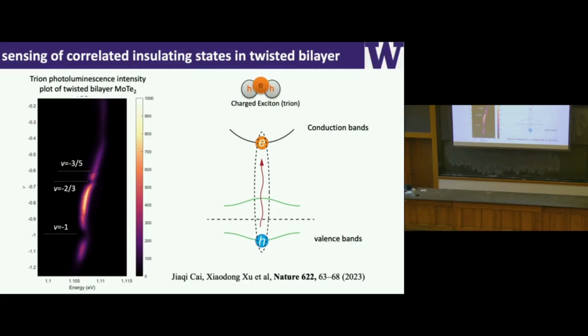Just to give you a simple picture of why trion luminescence is quenched at these fractional states: the simple argument is that the trion is an exciton bound to a fractional charge. So it requires an electron or hole population in the system. Whenever there's an incompressible state, the Fermi sea is gapped out, so the electron or hole population is decreased. When you have a reduced population of charges, then there's a reduced population of trions. And this reduced population is evident by the quenched luminescence.